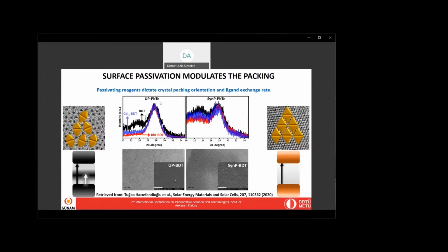Whereas if we apply the same thing for unpassivated quantum dots, we've seen that for some of the regions, the 1-1-1 diffraction pattern is lost, and we don't see a long range order, and they are not ordered in a way that we want for a photovoltaic cell, basically.